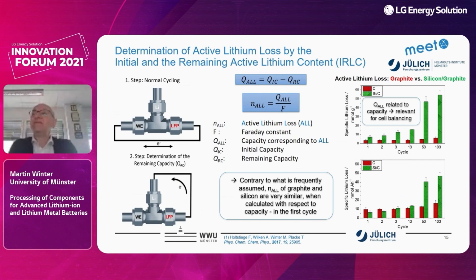And if we look at the specific lithium loss in millimole per ampere hour, we see here that in the first two cycles, cycle number 1 and cycle number 2, the lithium loss on graphite per ampere hour is even larger than that of silicon. What a surprise. But only after cycle number 3 and the following cycles, because of continuous SEI formation, continuous lithium loss, the accumulated lithium losses are higher on the silicon material than on the graphite material. So this method actually tells us something which, counterintuitively, I think, we would have assumed differently.